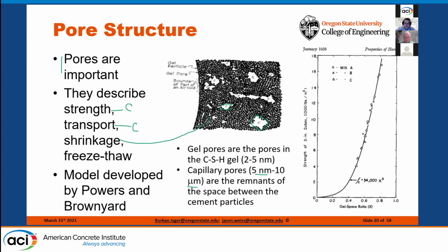So here we see the little tiny pores. These are the pores in the CSH. The gel pores are really driven by the shrinkage in the overall system. So these are the really tiny pores. And then freeze thaw is going to be driven by these great big pores that we didn't even show, which are the air entrained pores. So again, porosity is going to be very, very crucial for these systems.